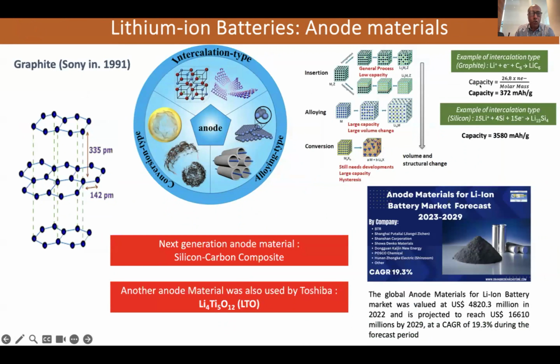And if you make a calculation of the capacity, you see here we can have a capacity of around 370 milliamp-hours per gram. But we also have a new good anode material, silicon. With silicon, we can get about 10 times what we have with graphite, but we have some problems with silicon. And the future, this is an indication for the young people, is to use a mixture of silicon and carbon composite as the anode.